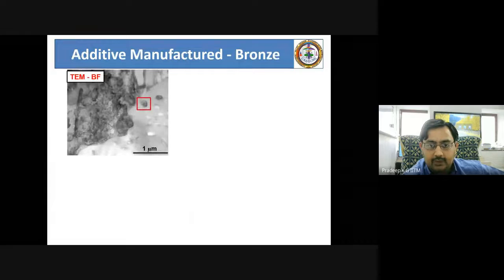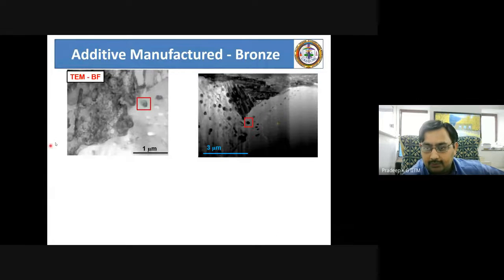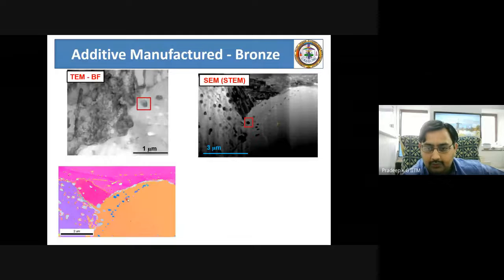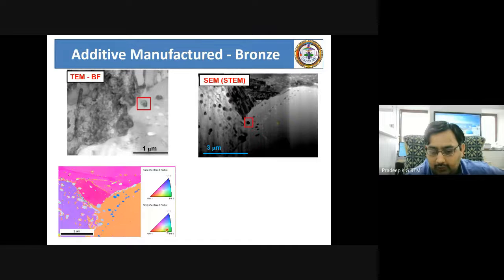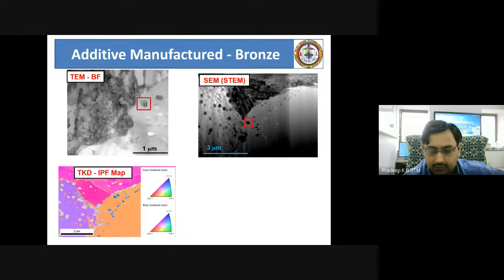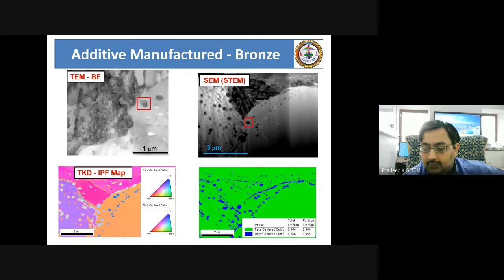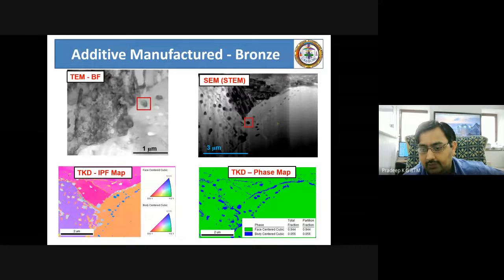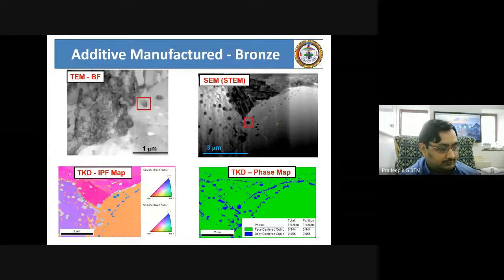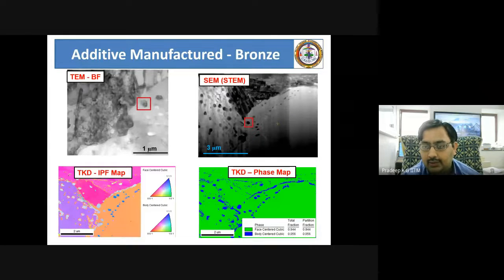So this is another example of a same precipitate identified using a STEM image with a large enough field of view in the scanning electron microscope geometry, and you can do the diffraction, and then you can get the orientation information of the same precipitate what you see here with respect to their 111 or 101 direction, and then you can also get their crystallographic structure based mapping, where you can see whether this is a body-centered cubic structure precipitate or a face-centered cubic structure precipitate. So all of this information you can get from the same location. So this is a uniqueness about characterizing nanoscale features in order to understand their mechanical properties.